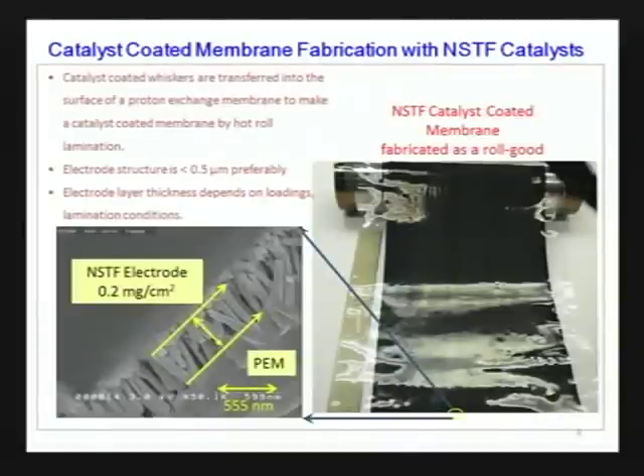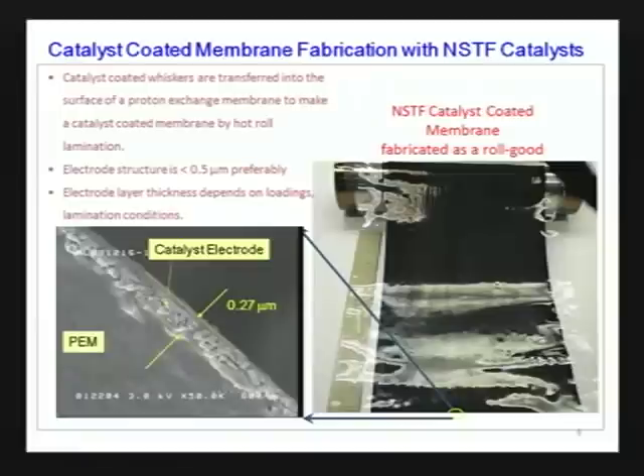We then take those catalysts and apply them to both sides of a roll-good membrane to make a composite membrane electrode assembly. And you can see by the expanded image on the left that the whiskers are penetrating into the membrane. Actually, how much they penetrate depends on the loadings, and for example, for the lower loading materials that we use for automotive, it's actually a very thin layer indeed.